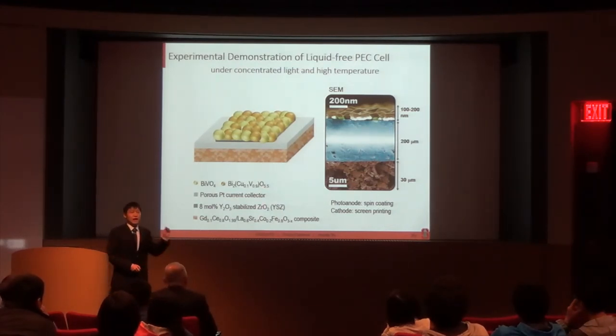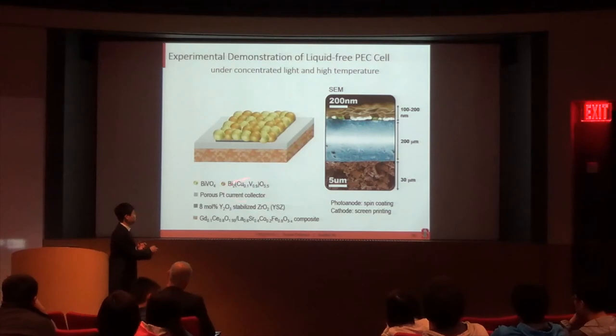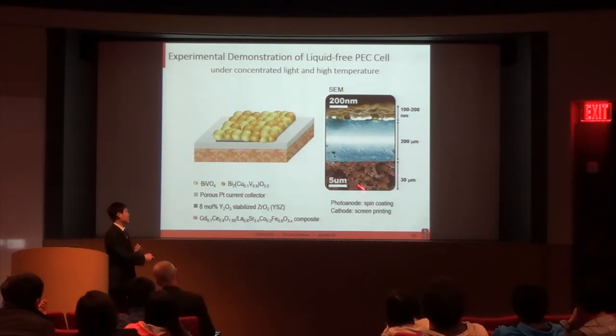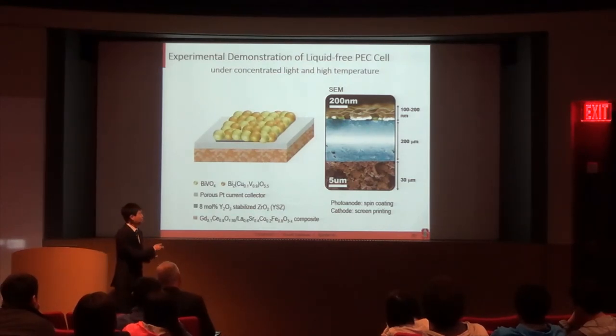And second, as the ionic conductor, I use this calcium-doped bismuth vanadium oxide, which is well known for its oxygen ion conduction at intermediate temperatures around 400 degrees Celsius. And we also expect this material to form better interface with bismuth vanadate because they share some similar elements. And we went ahead and fabricated the device based on this schematic. The electrolyte and the counter electrode are traditional materials from solid oxide fuel cells. The photoanode is deposited by spin coating.